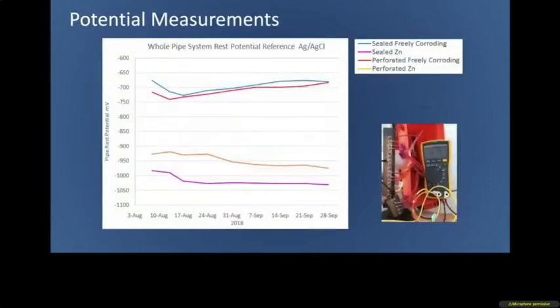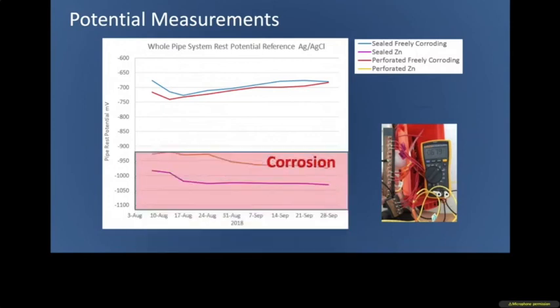We then get into potential measurements. And one of the ways that corrosion engineers basically discern whether a steel structure is corroding or is protected is by measuring the potential. And we do this with a reference electrode, which is called a silver-silver chloride reference electrode in this circumstance. We connect it to the common of a voltmeter, and we ground the voltmeter to the pipe, and we get a potential measurement.